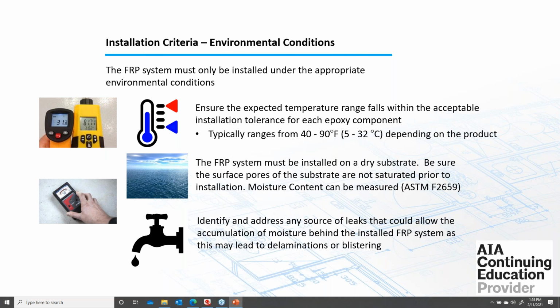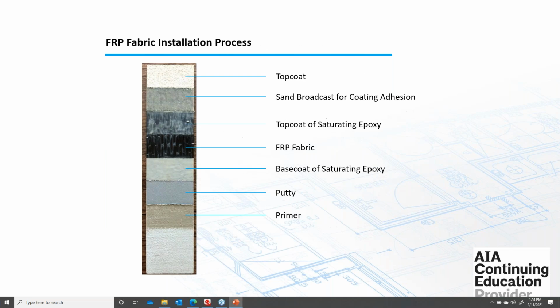You also have to identify and address any source of potential leaks that could allow the accumulation of moisture behind the installed FRP system, as this may lead to delaminations or blistering. Also note that the temperature of the substrate must be greater than the dew point by 3 degrees Celsius. This step is actually a critical check to do, especially for exterior applications. Next slide.